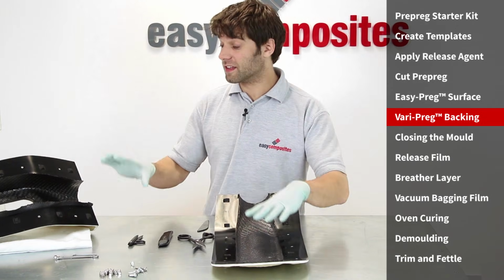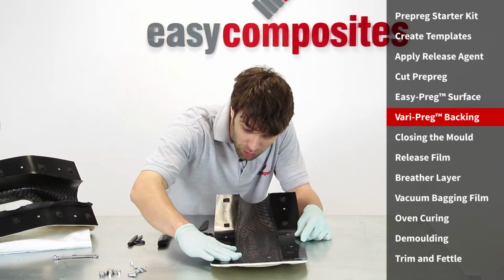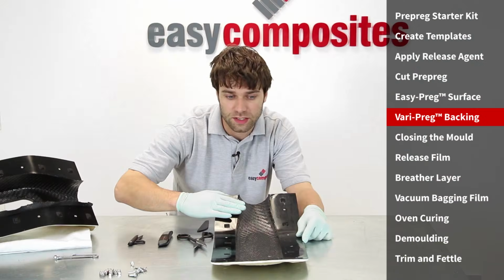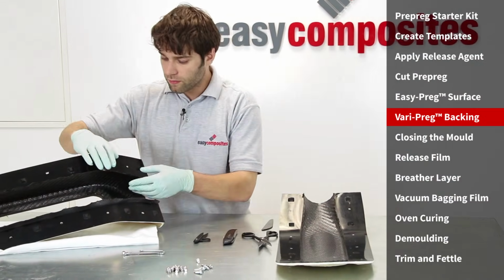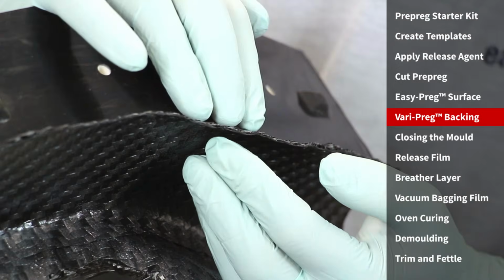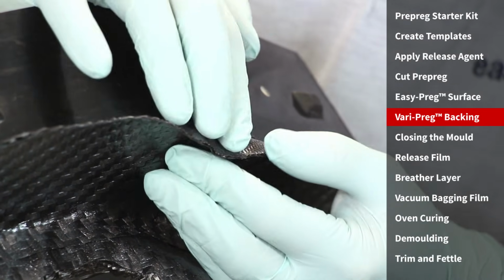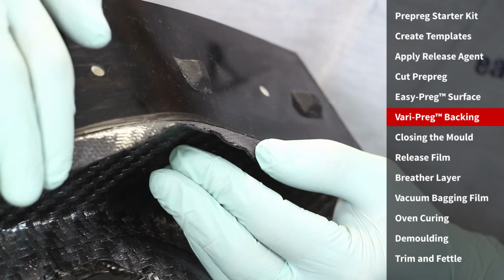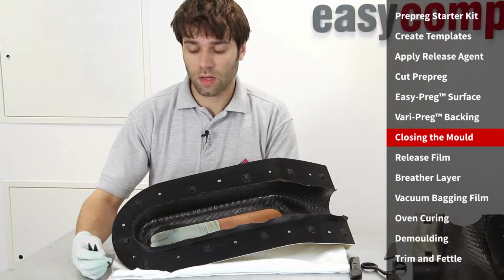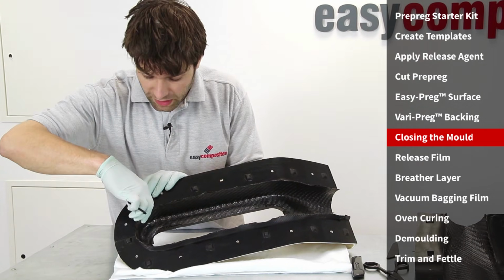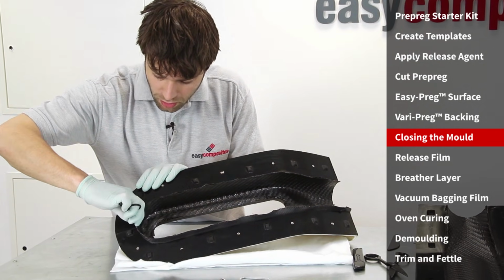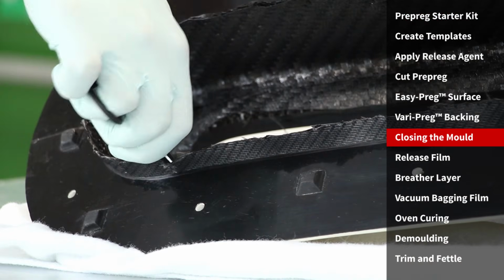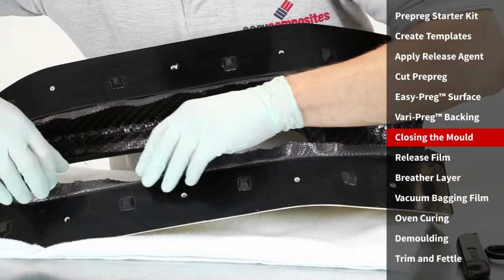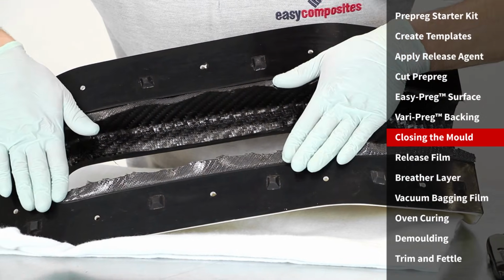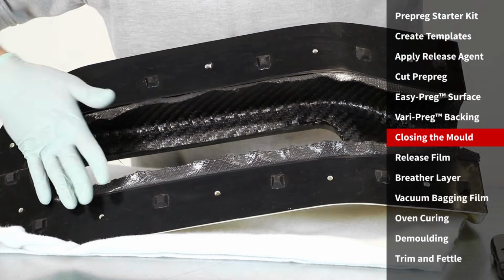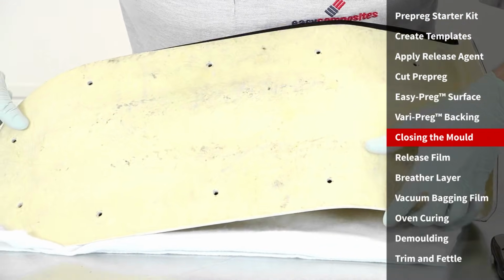That's the pre-preg carbon laid into both of these two parts. You can see on this one, we've cut the carbon completely level with the flange there, whereas on the other half, we've left around about 15mm on the top. That 15mm flap will be folded in, but then we'll join the two together when we come to the vacuum bagging stage. I'm going to put a few small snips into the carbon around the corner here to allow the flaps to be folded in without creasing. We'll fold these over and give them a quick press so that they're lying into the mould, and then quickly get the lid section on before they get a chance to straighten up.